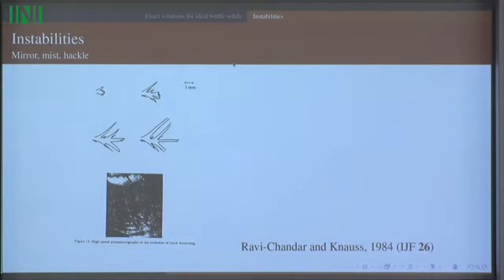Wolfgang Knauss and K. Ravi Chandar had proposed a mechanism for this in 1984, which I really took a long time to realize was the same thing, but they proposed that as cracks went along, they could become unstable to sending off branches that were at an angle to their direction of motion, and they drew cartoons to this effect, which I've illustrated here in the 1984 study of crack branching in plexiglass.